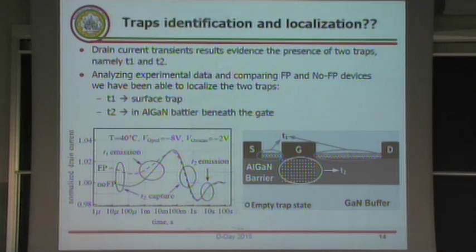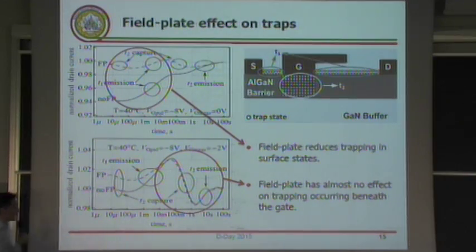But we also verified this localization by numerical simulation. I would like to show you the very interesting result we obtained: the presence of the field plate strongly limits the surface trapping because it reduces the electric field in this area, and so it reduces the amount of electrons injected into these traps.